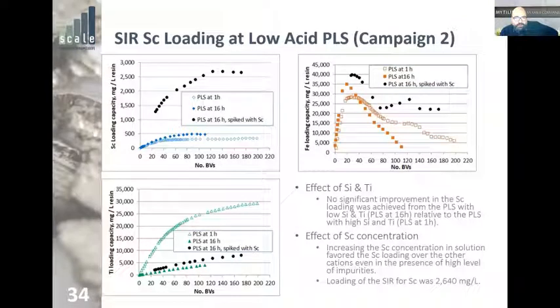To understand a bit better, there's also the test with the black circles. This is the same PLS as the 16-hour, but it has been spiked with scandium to see if the resin works in this region or not. And as you can see with the spiked scandium, so instead of 7 ppm, we now have 60 ppm of scandium in our solution. You can see that the resin responds much better and exceeds 2,500 milligrams per liter, indicating that the problem we have is that the scandium concentration is too low, again, in relationship to the impurities in the solution.